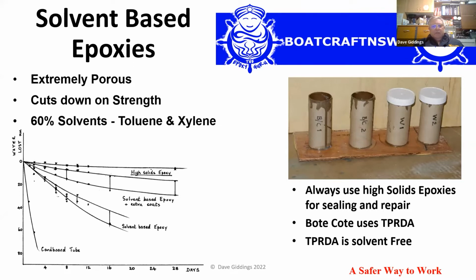They're known irritants. And the solvent molecules are a lot larger than water molecules. So by having that amount of solvent in there, that's got to leach out for the epoxy to go off. And it leaves the epoxy porous. So it cuts down on its water resistance and its strength.